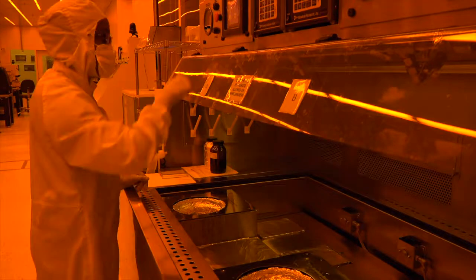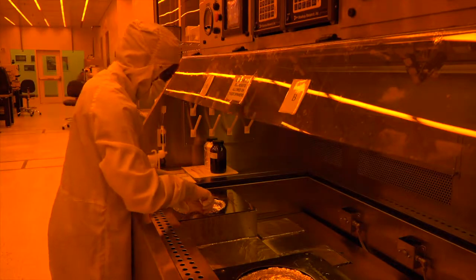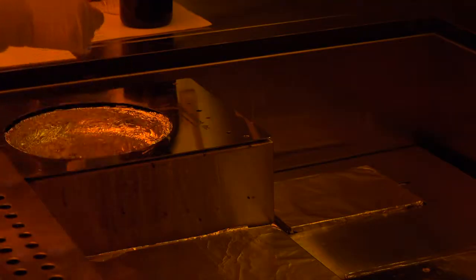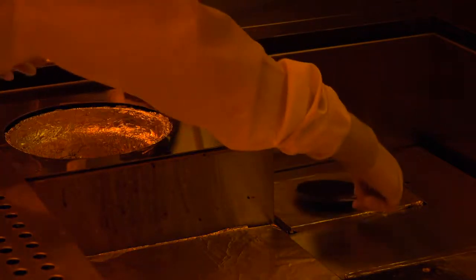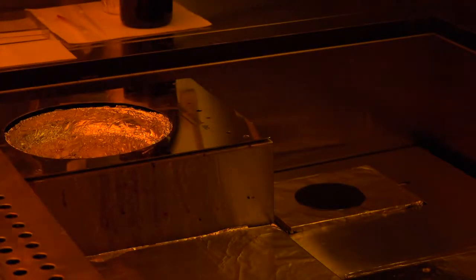After spinning the photoresist, we remove the wafer from the spin coater and bake the wafer on a hot plate at 115 degrees Celsius for 1 minute. The bake time and temperature can vary depending on the photoresist being used. The bake removes any remaining solvent from the liquid resist and solidifies it into a solid thin polymer film. This particular resist forms a polymer film that is 1.5 micrometers thick. For comparison, the width of a human hair is about 100 micrometers. So this film is quite thin.